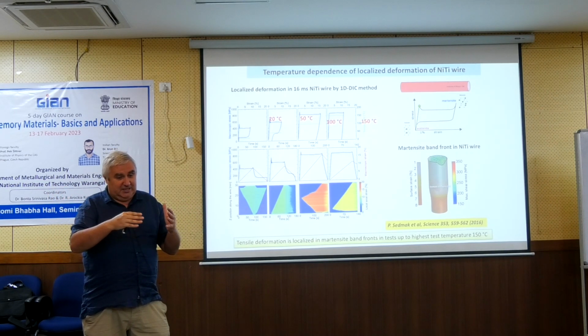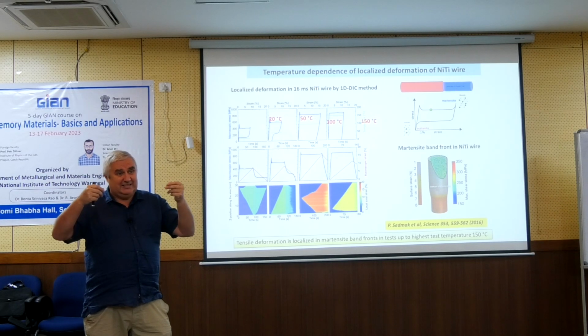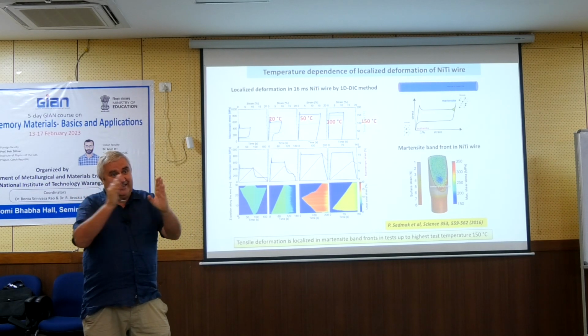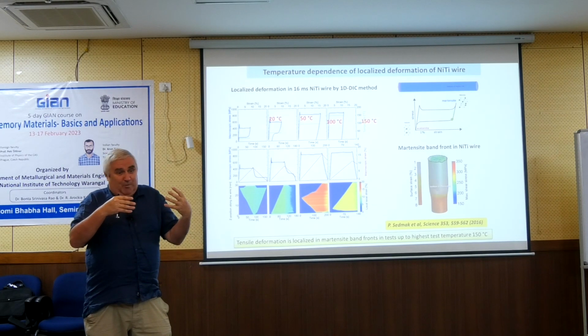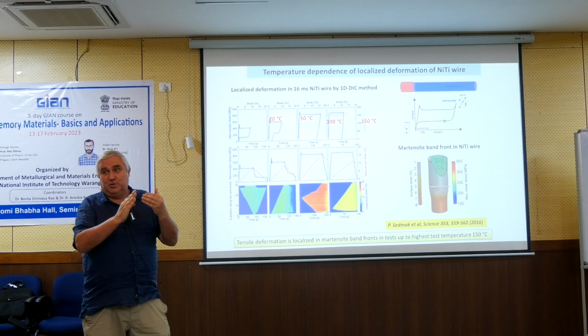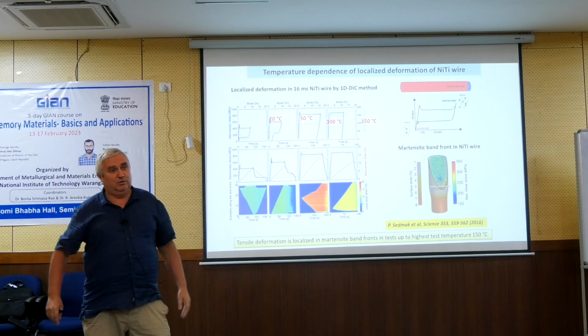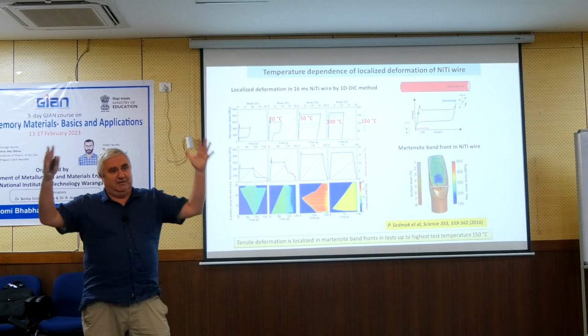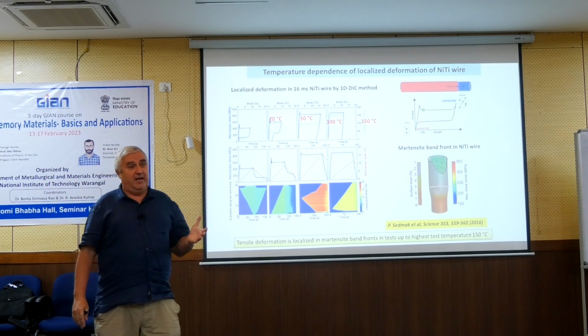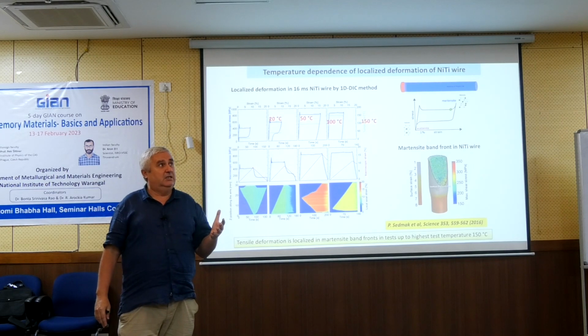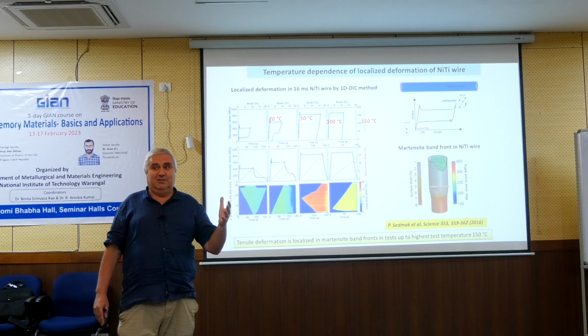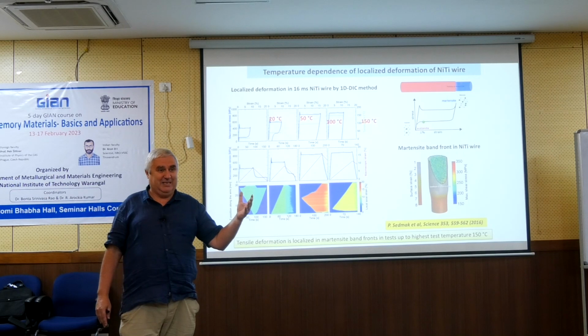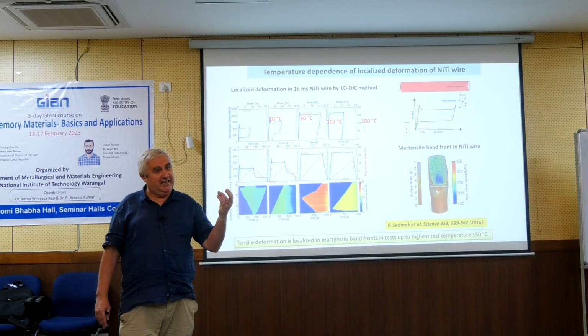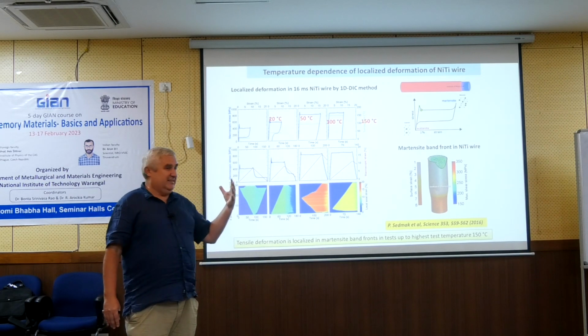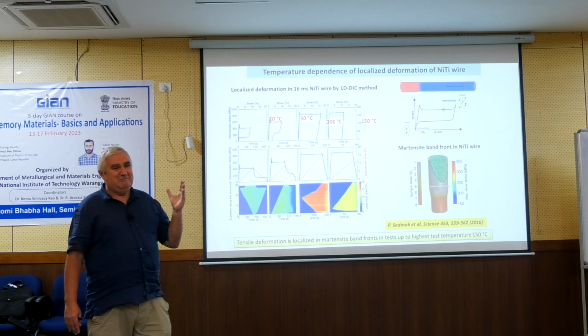But here, this elasticity is not Hooke elasticity, but elasticity due to this finite strain gradient and motion of the interfaces. Probably the motion of interfaces is associated with the energy dissipation. This is what most of the people believe in. There is a big energetic framework developed on it, and in fact, understanding how the energy is dissipated, you can develop a good thermomechanical model of SMA materials. So it's very interesting, but my talk is not about it. It's a very good question.